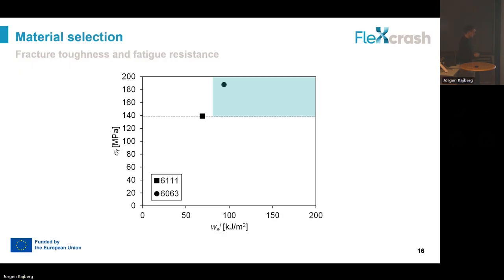And in this case, it makes sense to simply use this graph. I mean, this is only for these 2 aluminum alloys that we're investigating here in the FlexCrash project. But the main idea is to plot this fatigue strength for all different materials against the fracture toughness values, and define different regions where we can clearly identify which is the best material for each application. So here you can clearly see that there is a huge difference between the 6111 and the 6063, and it makes sense to select this material to obtain this folding behavior during crash, but also to have the good fatigue resistance when we are talking about using this material for chassis applications.